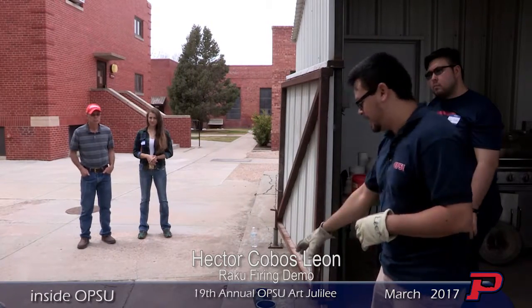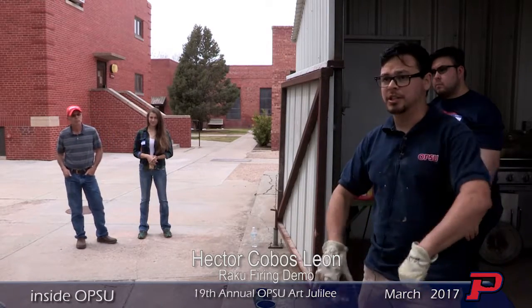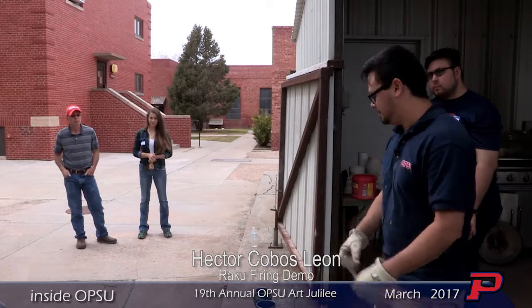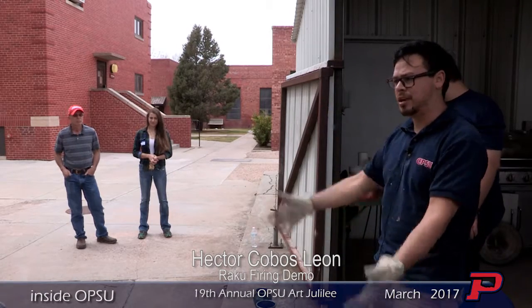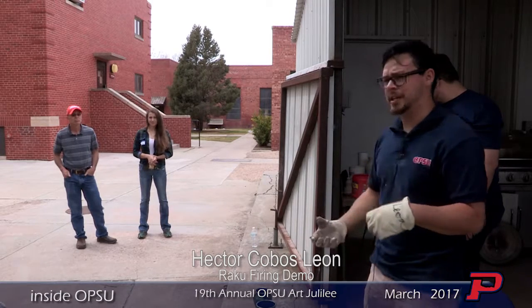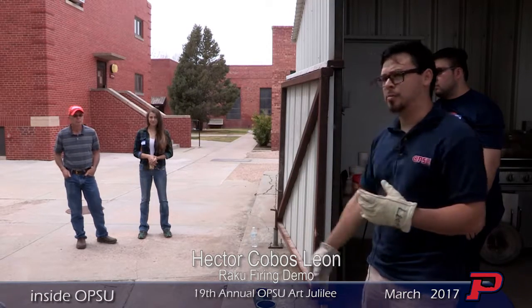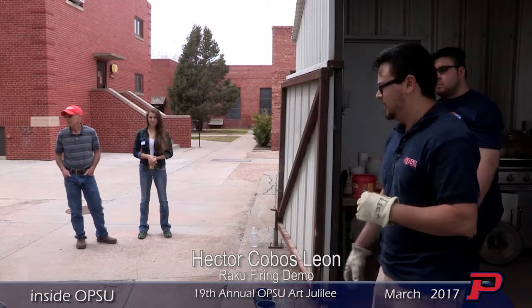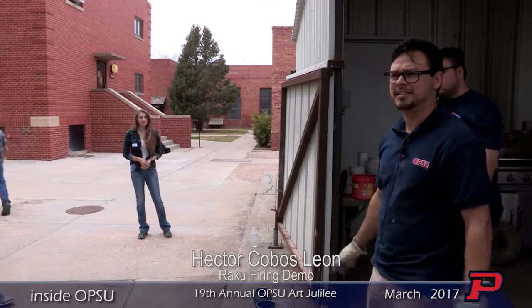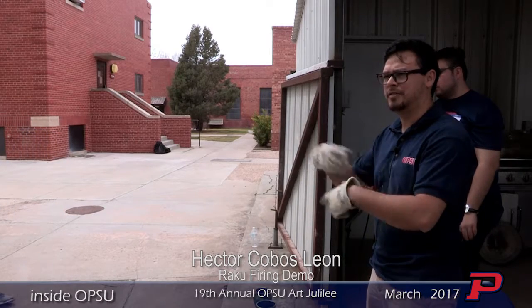What is it going to take for me to get copper? If I want copper, I'm going to have to reduce it, right? On its own, a bunch more paper. Don't burp it, don't open the lid. Otherwise, you'll get variations. If I want a copper red vase, 3 feet tall, I'm going to have to work with a white stoneware because my dark stoneware doesn't work well with the red that I use, or porcelain slip it and then apply the red. So different things. A changes B, B changes C, C will mess you up. Each thing has a different effect. It's kind of like a real snowball effect.